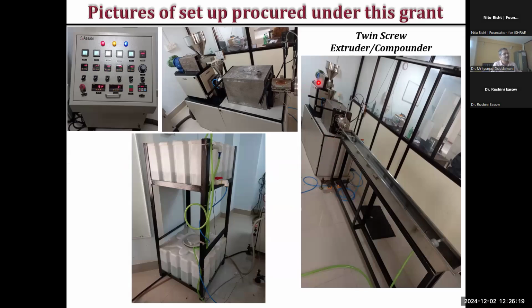So this is the twin screw extruder system. There are 2 barrels here, and this is a parallel type. There are 2 types of twin screw extruders: one is parallel, another is conical. Conical type we use when we introduce metal powders in the polymers, because we need a higher thrust and pressure. But here, as we did not intend to go for any metal powder system, we went ahead based on our domain expertise. We said a parallel screw is sufficient. So this is a parallel screw system.